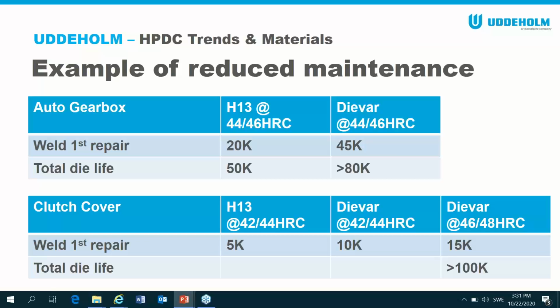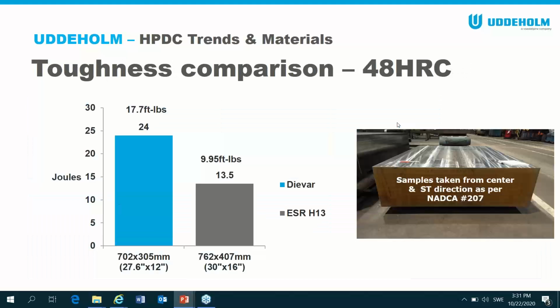But then they used their own initiative. They went up from 46 to 48 Rockwell, and they got 15,000 shots. So you see a practical example of that higher hardness giving less heat checking as you go along. And they get well over 100,000 shots on that die.